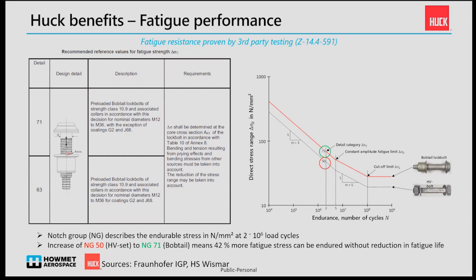And here on the right-hand side, as used in the Eurocode, you see the so-called notch group. So for our bobtail lock bolts, we achieve a notch group of 71, which is 71 Newton per square millimeter of fatigue resistance, compared to 50 Newtons per square millimeter at 2 million cycles for a conventional threaded HV bolt.